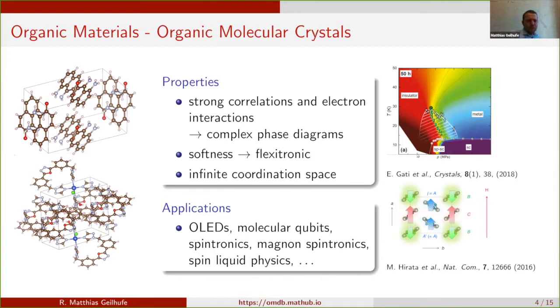There are a couple of examples shown on the right for BDT, TTF based organics, where I just want to show that, depending on temperature and pressure, you already see various different phases, with superconductivity and different kinds of superconducting order. Or below, you can see the emergent molecular magnetism, also in a BDT compound under pressure, where you have nominally non-magnetic molecules, which then in this crystallographic framework start to polarize their magnetization due to the strong interactions.